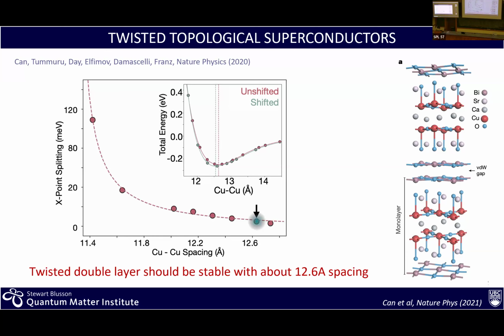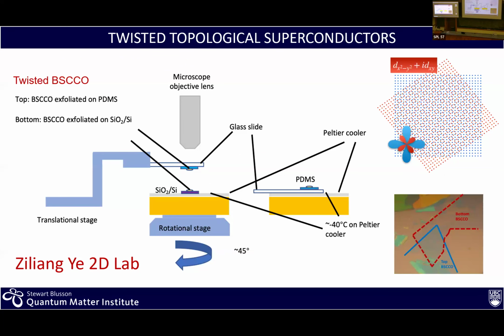Okay, well, so this is, of course, the prediction now, and how do you make it? Well, the idea is to do pretty much the same that you do in bilayer graphene. So you have to have a way of working in an inert atmosphere. Now you have a polymer here in blue holding a bismuth cuprate crystal. Here you have a silicon oxide substrate.